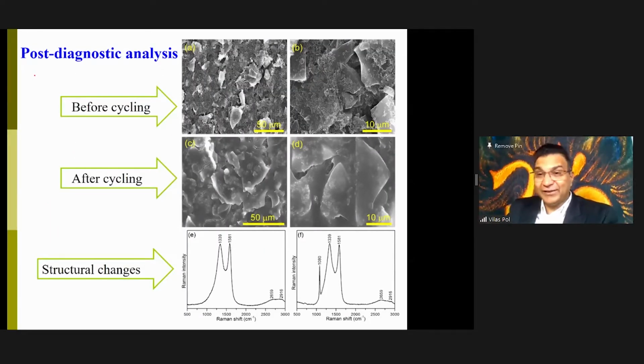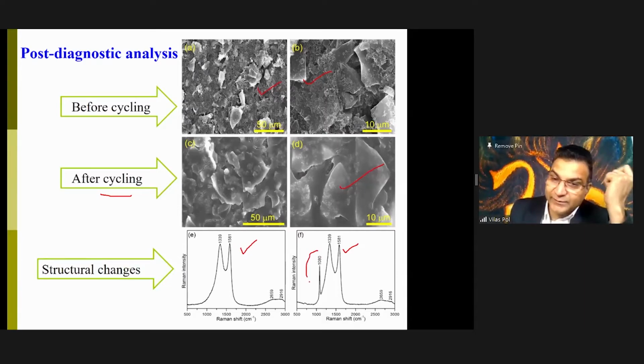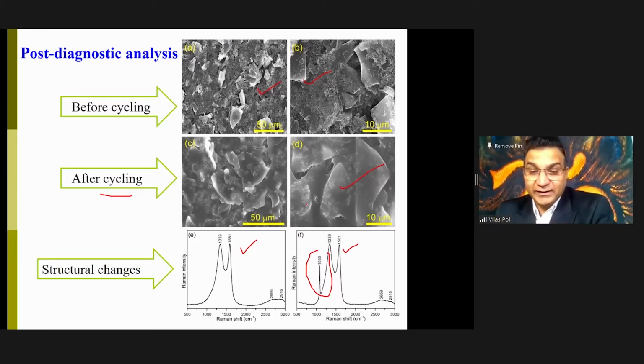Those batteries were cycled, charged, discharged, and finally we opened them to find out what happened to the sheets that we put inside the battery. Did they disintegrate or whatever happened to them? This is the original material, put inside the battery in the presence of some binder because we have to hold them together. And after cycling, after aging the battery, the sheets are there. And that means the packing peanut derived sustainable material is robust enough to survive inside the battery. And then we did some characterization to understand that the structure also did not change. So morphology is the same, structure is the same. There is a small additional peak that is because of the electrolyte decomposition that happened inside the battery. So as such, we can say that those batteries are really doing well and not having any trouble.